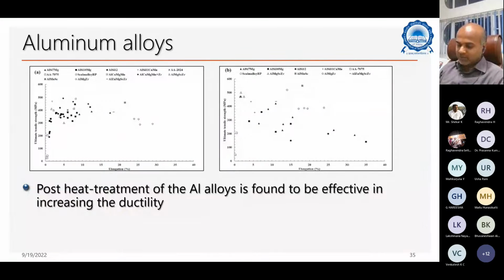In aluminum alloys, this is as deposited, and this is after heat treatment. These are the as-deposited ones. We look at the ultimate tensile strength versus elongation, which I'm trying to plot. Very few alloys exhibit around 30% elongation. Most of the alloys will have less than 10% elongation.